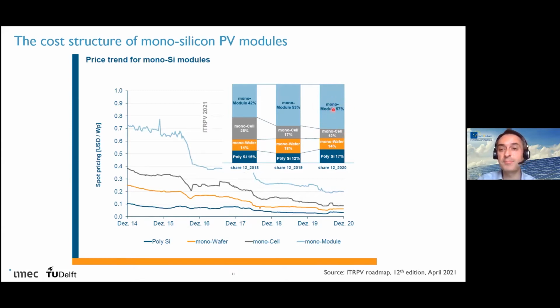Roughly 60% of the module cost really comes from the materials and processes needed to interconnect the cells and encapsulate them. So materials include the encapsulation material, but also the glass and so on. It's interesting to see this breakdown of the cost structure, because this has evolved a lot over time. Until a few years ago, for instance, the cost of the cell processing was relatively much higher. But now it's dominated really by the module cost and the crystalline silicon cost.